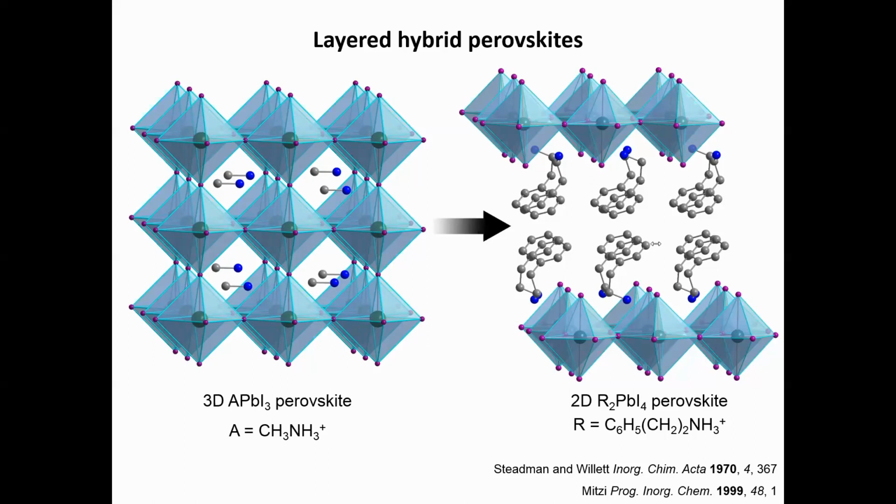Yeah, so once you have the recipe, like the concentrations, the solution, the temperature, things like that, it's really quite easy. It literally is take a pot of water, throw in lead bromide and the bromide salt of the organic ammonium, and you just allow it to crystallize. Even the crystallization is pretty simple. Let the solvent evaporate or let another solvent diffuse in. So it's really simple once you figure out the conditions.